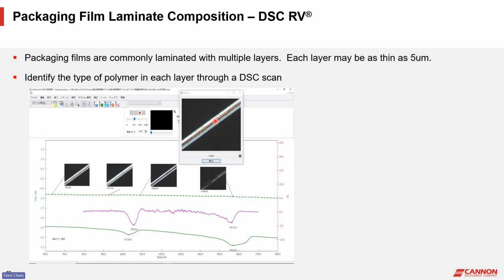Here we have a piece of unknown packaging film. Underneath the microscope, we can see that it has 3 layers. In a typical DSC temperature scan measurement, which is this green curve in this figure, we see 2 melting peaks, which are associated with the melting of polyethylene and polypropylene. So we know that this film may contain polyethylene and polypropylene layers. However, the question is, which layer is what?